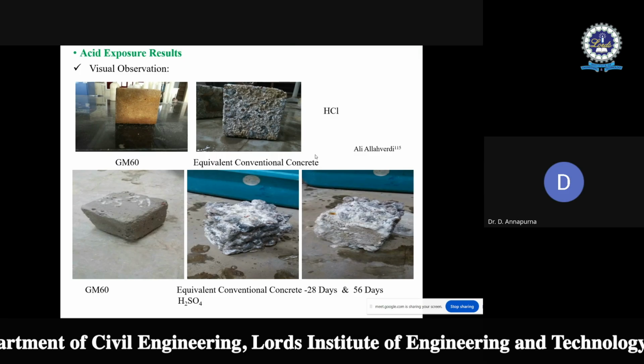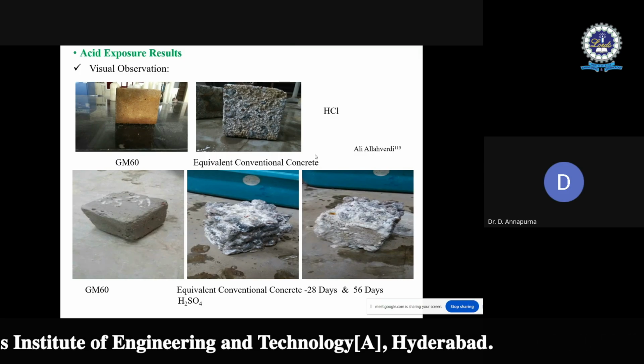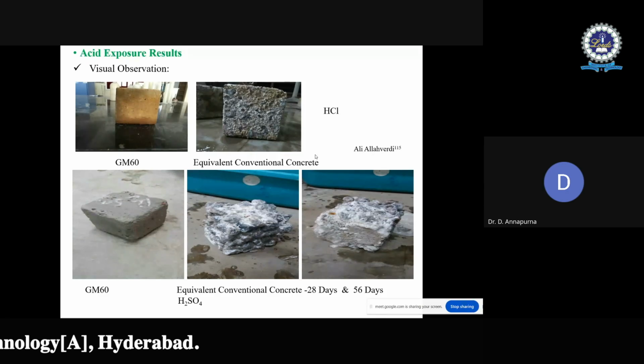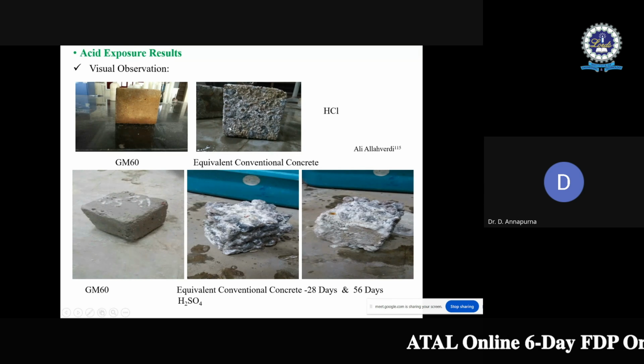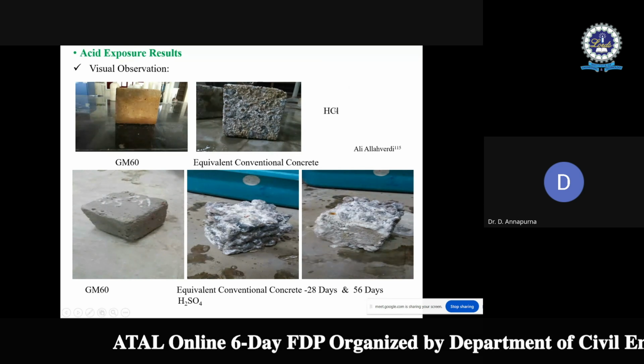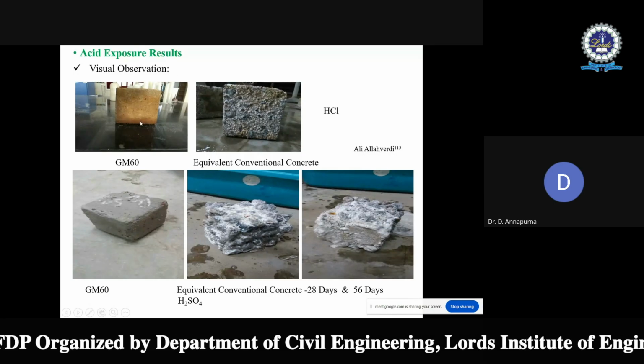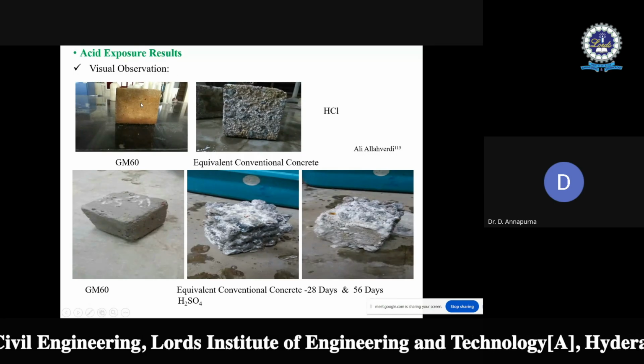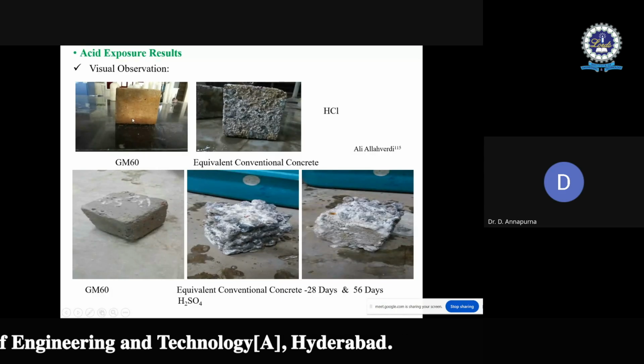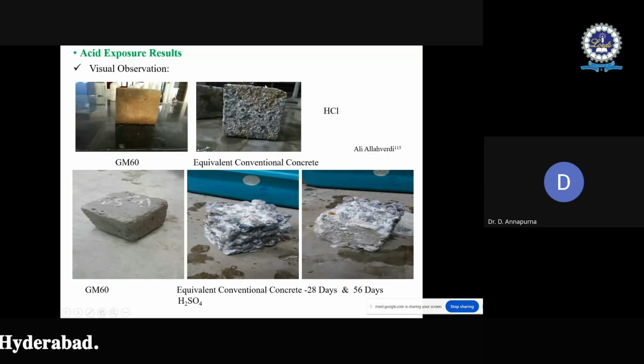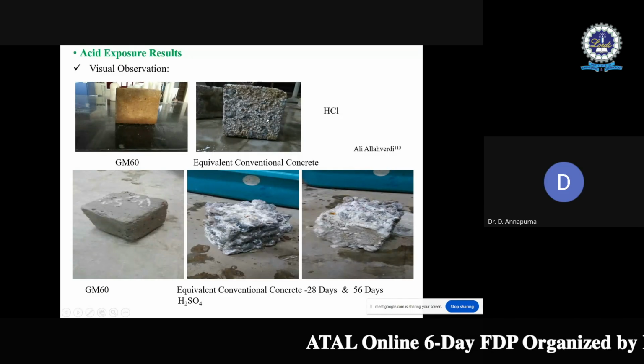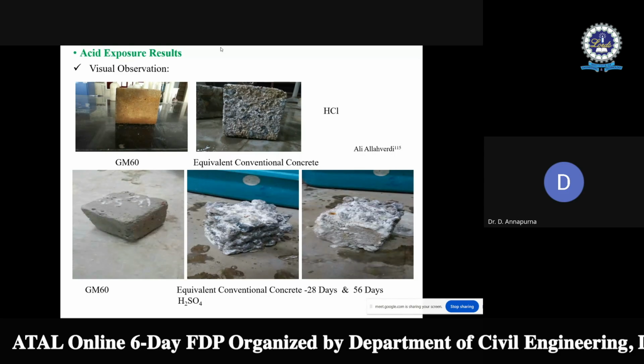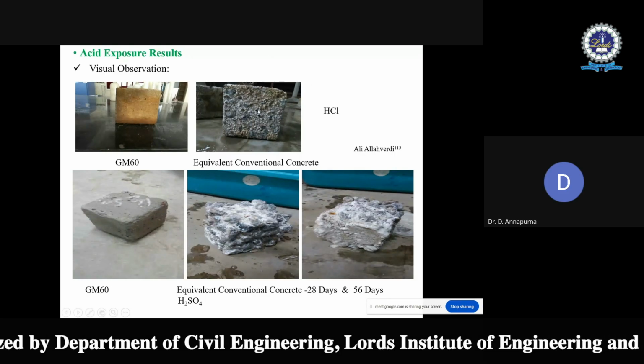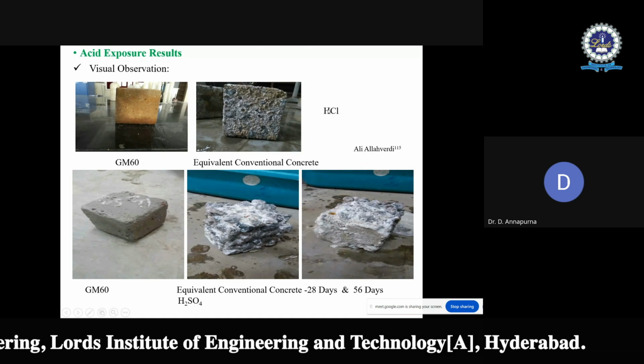Here two types of acids are considered, HCl, that is hydrochloric acid solution, and sulfuric acid. This GPC specimen, that is the geopolymer concrete specimen, is GM60, and this is conventional concrete. When they are exposed to the HCl solution, we can see that aggregate exposure has not happened in the geopolymer concrete, whereas in the conventional concrete we can see aggregate exposure. Removal of mortar has happened and aggregate exposure is seen on the samples when exposed to HCl solution.